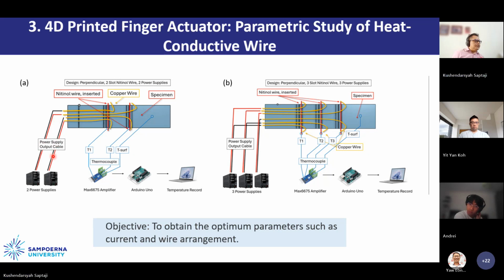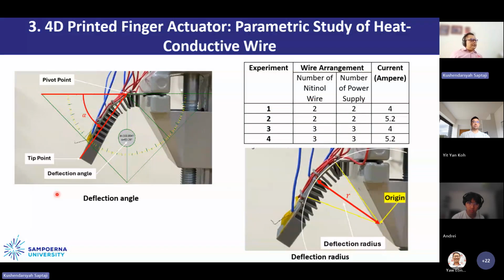give heat conduction into the PLA specimen. So we use 2 and 3 power supplies, and we measure the temperature at this wire using a thermocouple, and we record the reading. We apply 2 wires perpendicular to the finger and 3 wires like this. This is the side view of the experiment setup. Basically we measure the deflection angle, which is this alpha, from the horizontal line to the bending, and we also measure the deflection radius. Yeah, so this is the radius that we set.